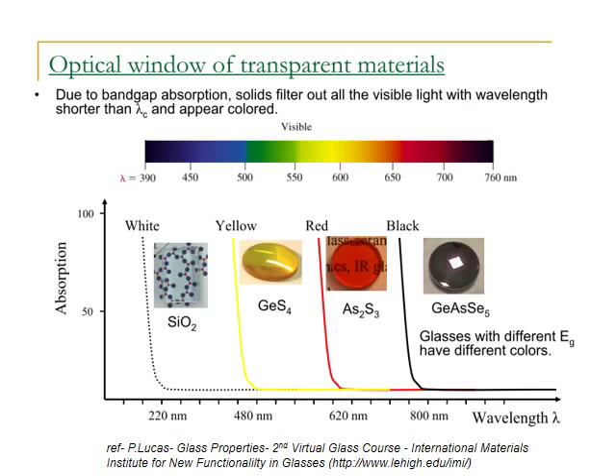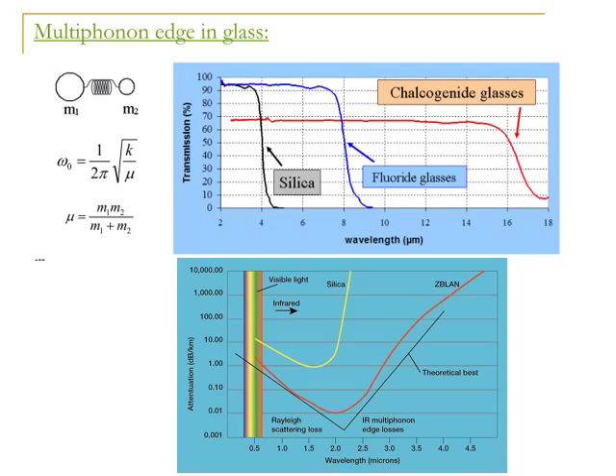These are the absorption spectra for some glasses. You see that materials displaying colors spanning the visible range can be prepared. At the lower energy side, the so-called multiphonon edge will define the transparency window. The simplest model for a bond is the one that considers atoms as mass spheres and chemical bonds as coils. The heavier the constituents, the lower will be the energy of vibrational modes, whose harmonics will define the multiphonon edge. In this figure, you see the multiphonon edge for silica, fluorides, and chalcogenide glasses.